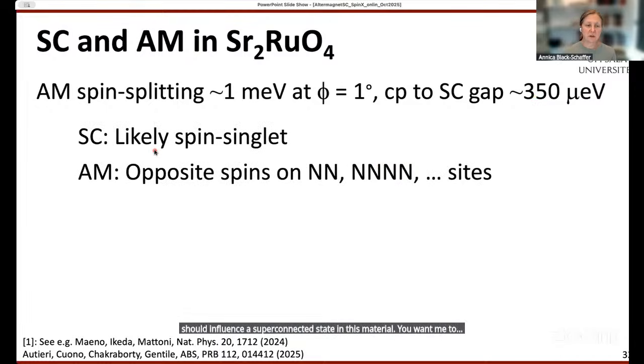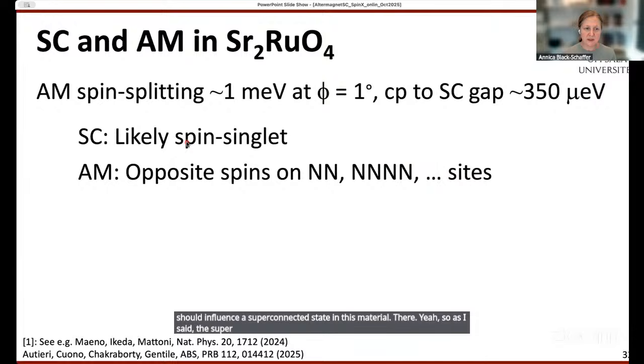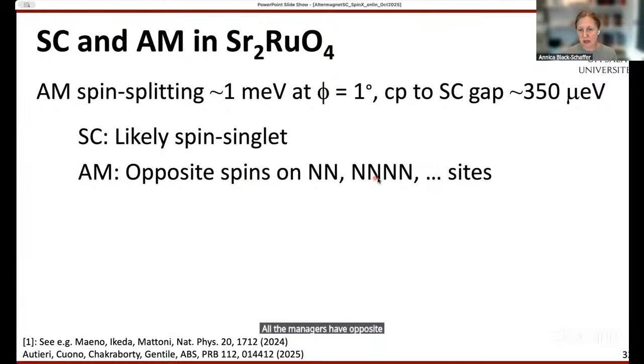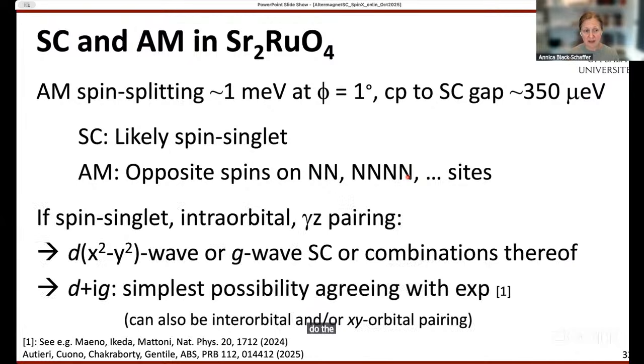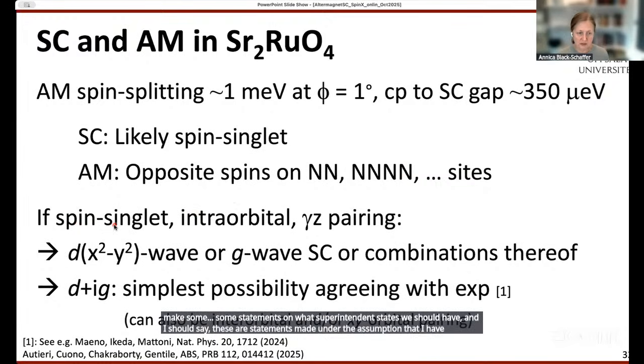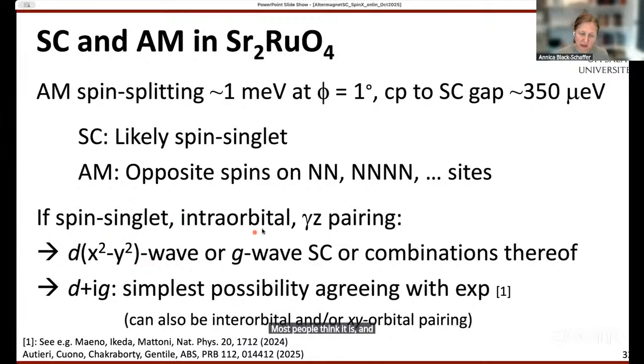As I said, the superconductivity is likely a spin singlet. The altermagnets have opposite spins on nearest neighbor and next nearest neighbor sites. So if you go back to the question of which superconducting states the altermagnet allows, then we can actually make some statements on what superconducting state we should have. And I should say, these statements are made under the assumption that I have a spin singlet, which seems to be what most people think it is, and that I only pair intra-orbital.